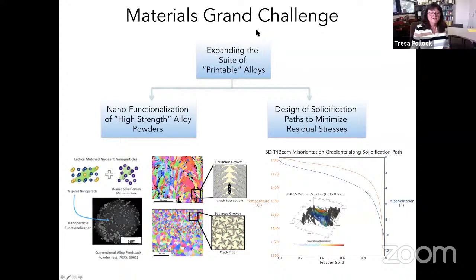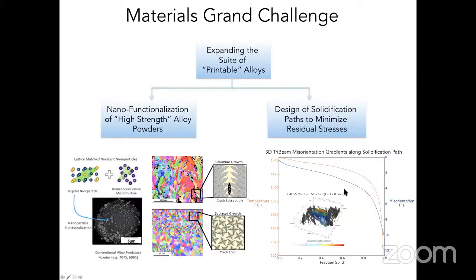One approach is to actually work with the powders themselves and try to go through processes where you functionalize the surface of the powders to enhance the nucleation process in the melt pool. And in doing that, you create finer grain structures, which have less tendency for cracking and hot tearing. And so this is quite useful for things like high strength aluminum alloys.